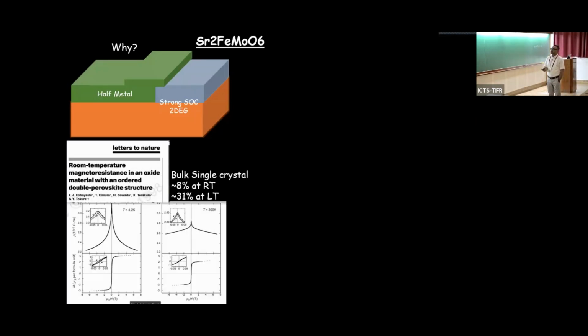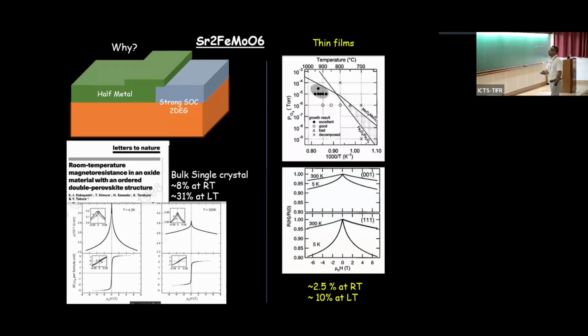And this material was shown to be a very highly spin polarized material with a high negative magnetoresistance, around 31% at low temperature and 8% at room temperature. And this was done on single crystal material. But the problem was that when people started working on thin films, they could never get more than 4 or 5% of this